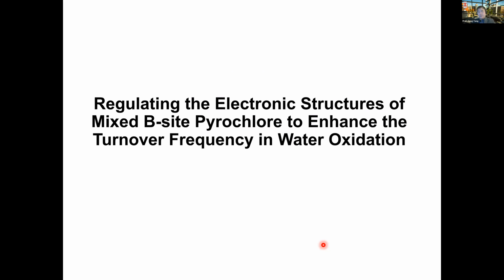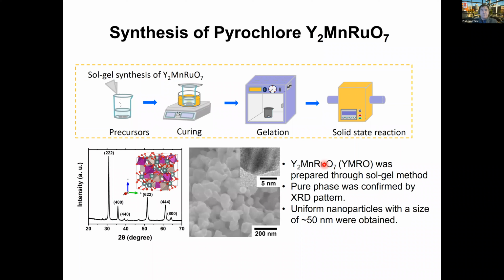So this is a size tuning in terms of improving the performance or the activity of this type. The first one is the electronic structure, which we think dominates the performance for these B-site pyrochlore structures in the OER catalyst system. The particular one that I'm going to introduce here uses manganese at almost 50% as a dopant for the ruthenates. This is probably another story for another day.